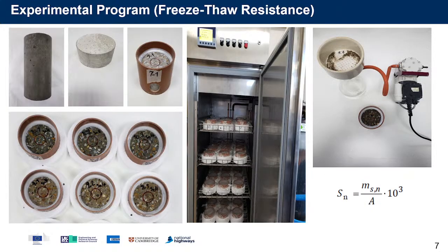And for freeze-thaw resistance with de-icing salt, I used the same method of sample preparation, but I used a 3% sodium chloride solution as a medium on top of the samples, and then I collected, filtered and weighed the mass of scaled material from the surface of the concrete.